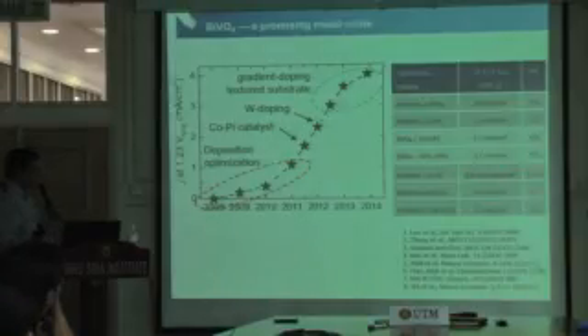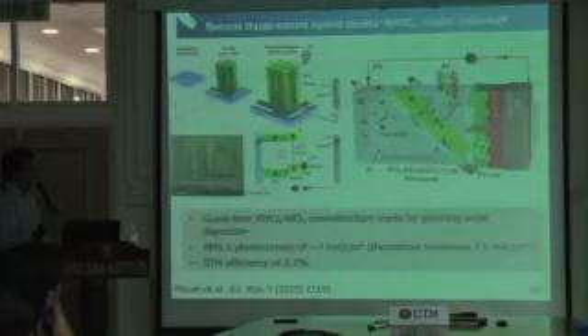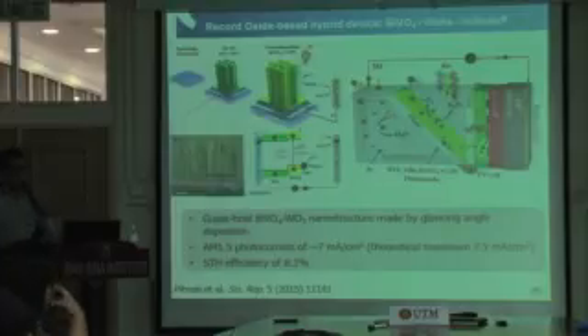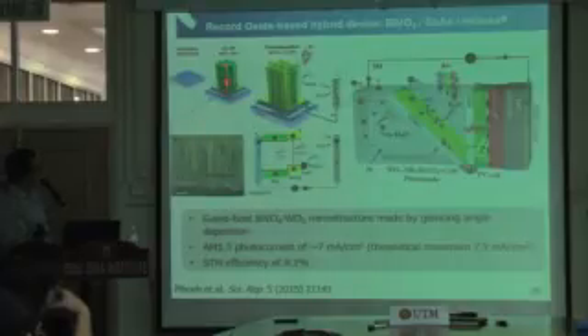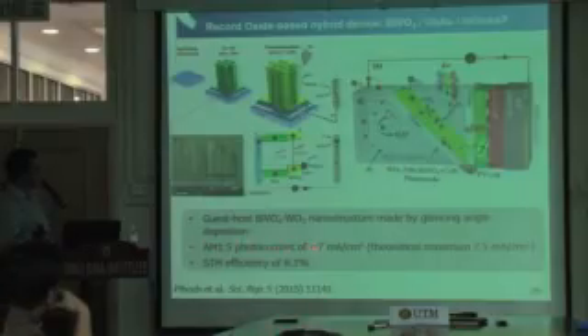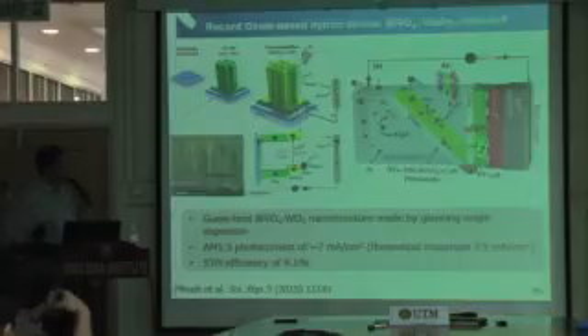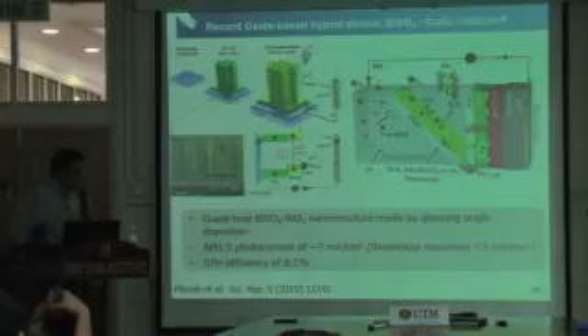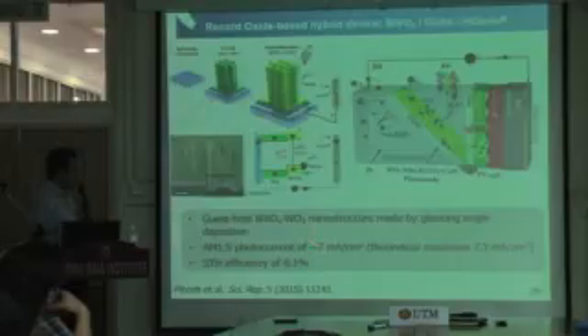photocurrent. And a very recent report, like a few months ago, also reported a very high-performing bismuth vanadate-based photoelectrode. They make a host-guest nanostructure. They have tungsten trioxide coated with a thin film of bismuth vanadate, tungsten oxide nanorods covered with bismuth vanadate, and they get an AM1.5 photocurrent of almost 7 milliamps per square centimeter. If you think about that, the theoretical maximum of this material is 7.5, so it's already 90%. So 90% is already achieved with bismuth vanadate.